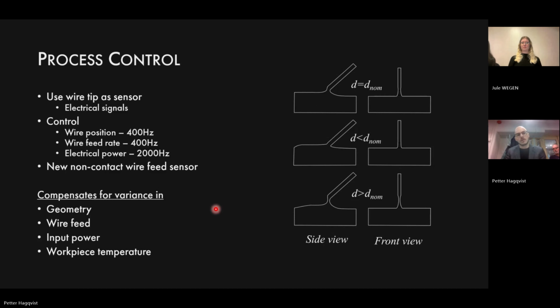So our controller compensates for variations in geometry, which could be due to a deforming substrate or a non-nominal substrate, if it's out of specifications in some way. It also compensates for variance in wire feed rate, because the wire feeder, we want it to always give us the feed rate that we ask of it, but it won't. There will always be some kind of variations.